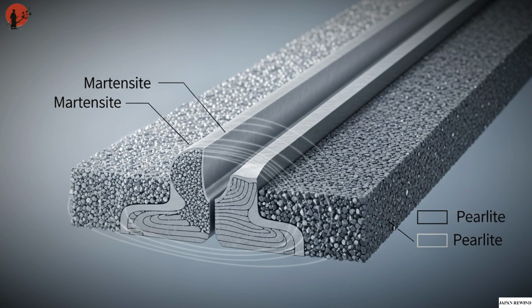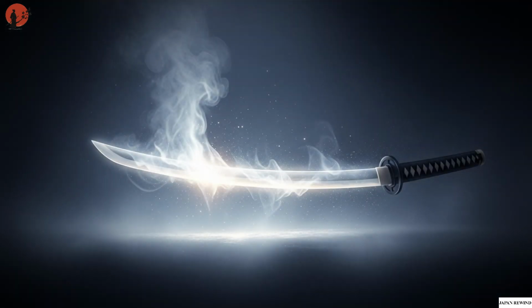The thinly coated edge cooled rapidly, transforming into martensite, a glass-hard, crystalline structure. The spine, insulated by thicker clay, cooled slower, forming pearlite, softer and more ductile. This difference in cooling caused internal tension, and the blade curved as a result. This curve wasn't hammered into shape. It emerged naturally, born from the collision of physics and spirit.